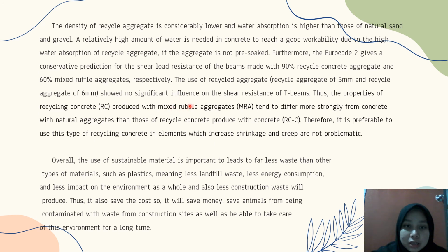Thus, the properties of recycled concrete, which is RC produced with mixed rubble aggregate, MRA, tend to differ more strongly from concrete with natural aggregates than those of recycled concrete produced with concrete, RC-C. Therefore, it is preferable to use this type of recycled concrete in elements where increased shrinkage and creep are not problematic.